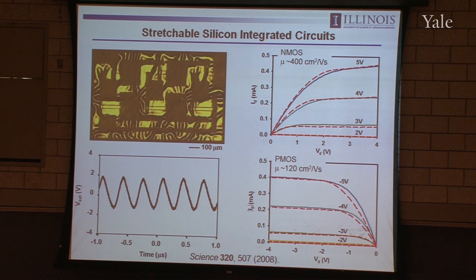Now there are a couple of disadvantages, and I've already mentioned one. One is limited range of stretchability. So you can stretch these about 15 to 20% in a practical sense before things start to break. And that's just a constraint associated with the physics of buckling. The other disadvantage is that these devices are not fully isolated from strain. So as you stretch this thing around, the silicon is experiencing some amount of strain, and strain actually changes the way that the devices operate by a modest amount. And that's not important for a lot of the applications we're interested in, but if you're imagining building a very sophisticated integrated circuit, that might be a problem. So strain isolation and strain range are two limitations of this design.